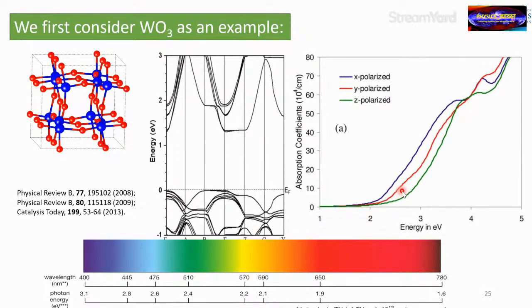So from the near infrared, everything should be absorbed. Now, when we calculated the optical absorption plot, what we found is that the absorption around 2 electron volt is not much. It's almost close to 0. 2 electron volt is around this color, not even on the red side, on the yellowish orange color. That means at the lowest gap, where we started from 1.4, this thing is not absorbing. As I mentioned, the gap could be small, but at the smallest gap, light absorption can be prohibited or forbidden because of some dipole selection rules. Those come from crystal symmetry. So we can see here one of the examples that light is not being absorbed, even though there are energy bands. Light is not being absorbed around 1.4. It started absorbing significantly after 2 electron volt.